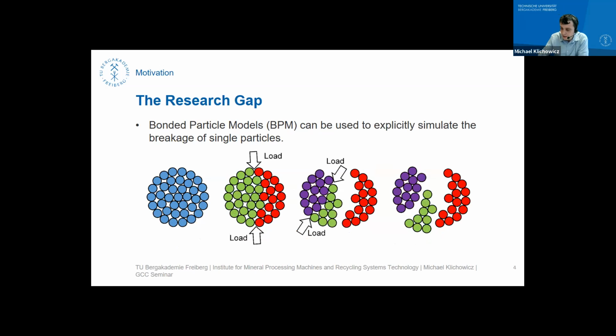And there are many approaches for simulating comminution, and maybe one is the bonded particle model, which can be applied in DEM, and that can be used to explicitly simulate the breakage of single particles. And I think everybody knows, if you have a bonded particle like the blue one, and you apply some load, and you have the correct good material law and a good parametrization, you can break this particle into the red and the green one. And if you continue in your simulation, you can even break the green particle further. So that is, in short, the idea of a bonded particle model.